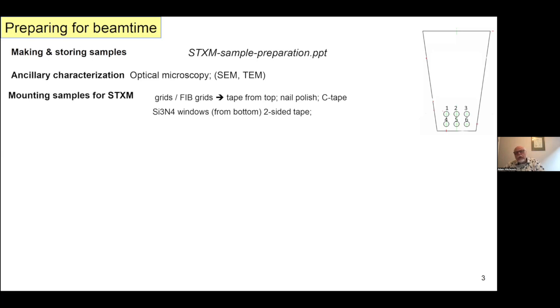Silicon nitride windows are a bit trickier. Taping them from the top usually doesn't work. They slide around too much. So you end up using something like double-sided tape from underneath or an adhesive at the edges.